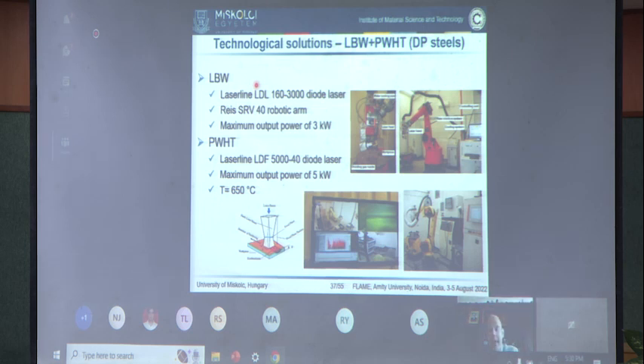Localized post-weld heat treating can also be performed, for example, in industrial practice by laser welding. Here you can see one of our experimental works where diode laser equipment was used for the welding of different kinds of dual phase steels. And afterwards, with similar diode laser equipment, we performed localized post-weld heat treatment with a top temperature of 650 degrees Celsius. Here you can see some information on the parameters.